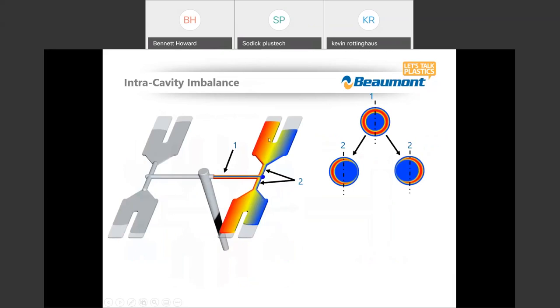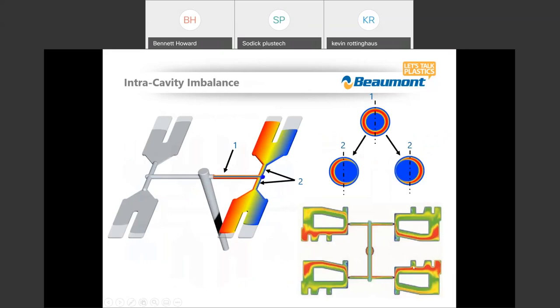So where one side of the part is receiving slightly higher shearing, less viscous laminates than another side of the part. So you can sometimes look at 4-cavity tools, and from a balance standpoint, we're getting off topic just a little bit here, from a balance standpoint in terms of weight, we'll look at these and they'll weigh the same. So a person would weigh these parts on a scale on a short shot and go, my tool is balanced, only from a standpoint of weight. From a standpoint of where those higher shearing laminates are developing within that cross section of that runner system and thereby influencing how it's filling a part, we can see differences.